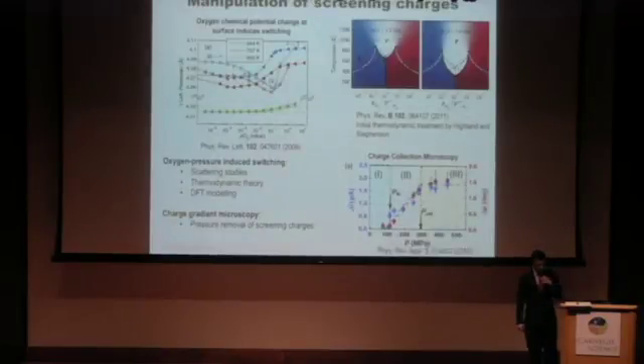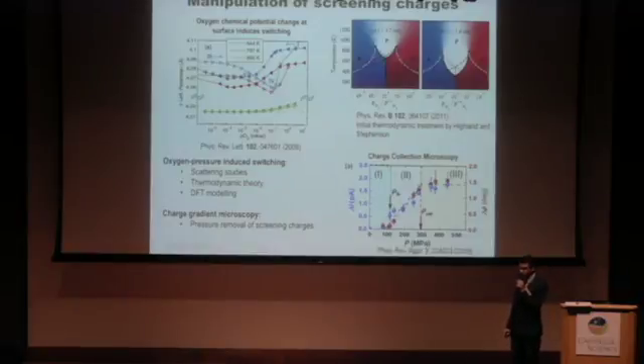One of the really good works in the last decade in ferroelectrics has to be coming out of Argonne, in this particular work by Highland and Stephenson. They took an ultra-thin ferroelectric film, lead titanate, I think less than 5 nanometers or so, put it into a chamber, and changed the partial pressure of oxygen at slightly higher temperatures. And what you clearly see is that by simply changing the partial pressure of oxygen, they're able to induce ferroelectric switching. So you see this nice butterfly hysteresis.